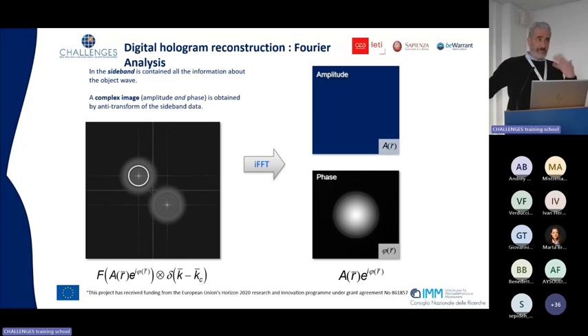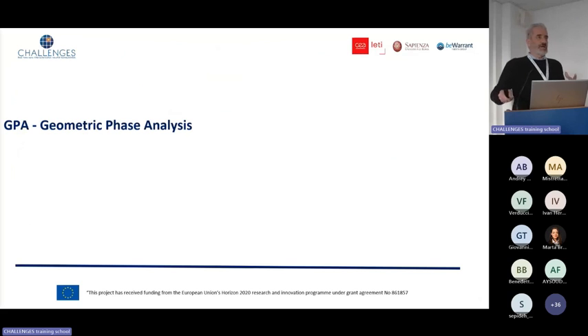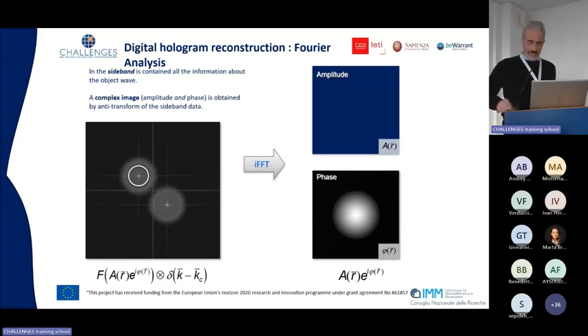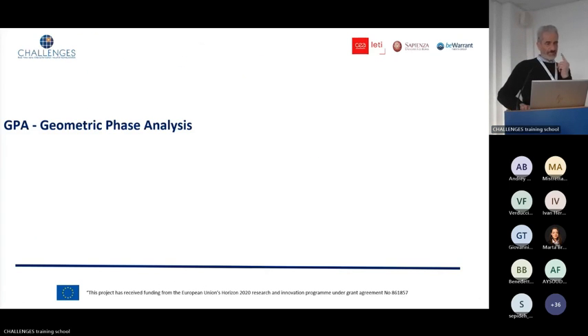So by reconstructing with the inverse Fourier transform procedure, you have a flat amplitude because we cancelled it, and the phase image in which the intensity is proportional to the local thickness of our sphere, of course. So we have a non-absorbing element. The electron passes through our object, only the phase of the incoming radiation is changed, and the phase is proportional to the local thickness, and the final image is proportional to the local thickness of our object.